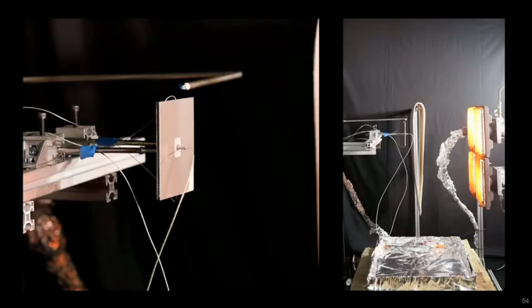In this particular experiment, the sample was exposed to a heat flux of 50 kilowatts per square meter, and you will have noticed in my report that we used heat fluxes of 25, 50, and 75 kilowatts per square meter in our experiments. This is essentially an experiment chosen at random to show you. This heat flux, 50 kilowatts per square meter, is broadly representative of that which would be experienced about 1.5 to 2 meters above the hearth in a typical BS 8414 large-scale cladding test.